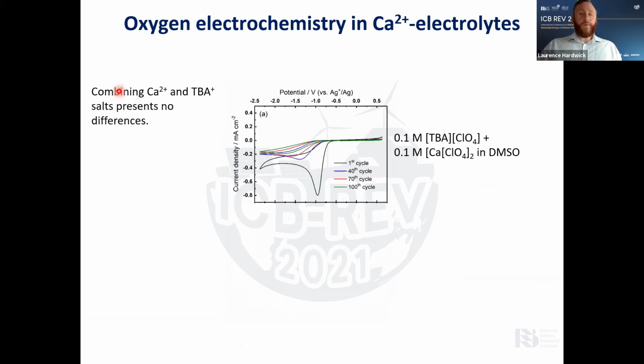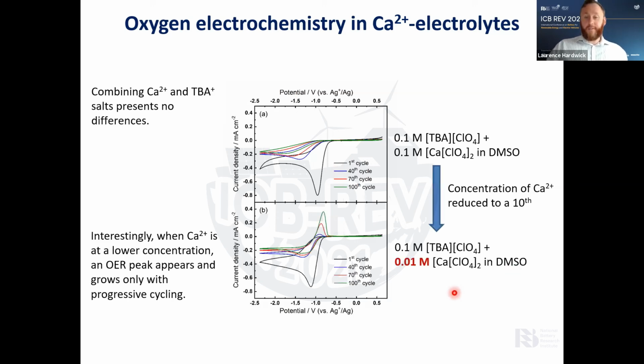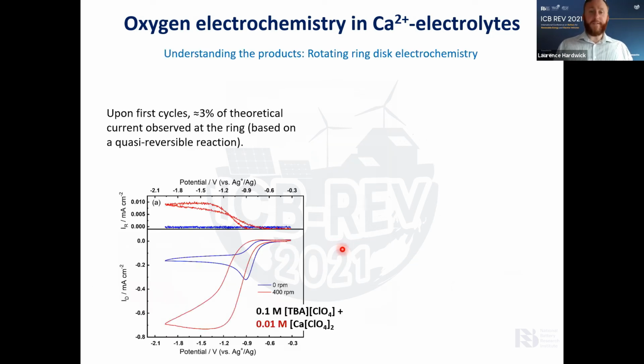So we did wonder whether, if we combine the calcium and the TBA, we'd get any improvement in the reversibility. And if we have similar concentrations, we again see this irreversible process that takes place. But if we reduce the calcium concentration by a factor of 10, after a number of cycles we start to observe the growth of an oxygen evolution peak. And so we were able to then oxidize some of the superoxide that we produce. We thought this was very, very interesting.